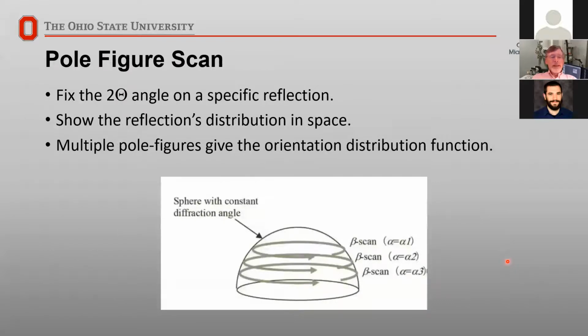So the idea here is that we set a particular 2 theta angle. If you remember back to our scattering scan, we had certain peaks. So we set our angles so that we're sitting right on one of the peaks, and then we can start spinning the sample around its normal and see where those peaks are relative in this part of the hemisphere, in this part of the hemisphere, and in this part. And then just work our way right up to the top of the hemisphere. So we're seeing where those planes are distributed through this hemisphere.